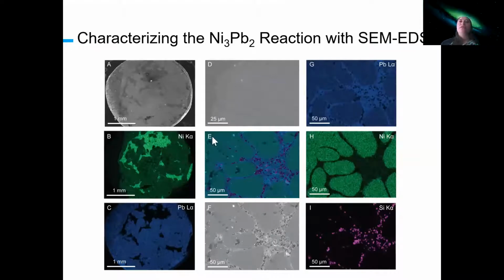And what I'm showing you here is the recovered pellet down to ambient pressure, ambient temperature. We have regions of elemental nickel, regions of elemental lead, but we also have mixed regions of both here, and they're color coded in these maps. And one of the interesting things that I noticed is that to prep these samples, you need to sand the surface of them. And the elemental lead ended up with silicon from the sandpaper material embedded in the grains, but the much harder intermetallic did not end up with the sandpaper embedded in it.